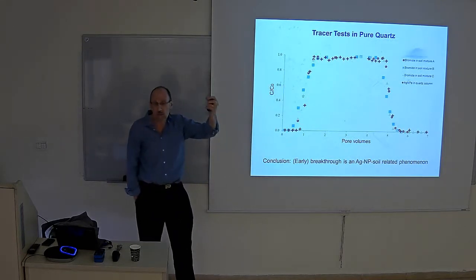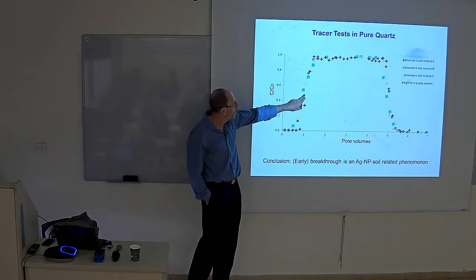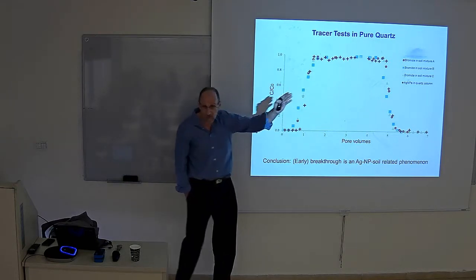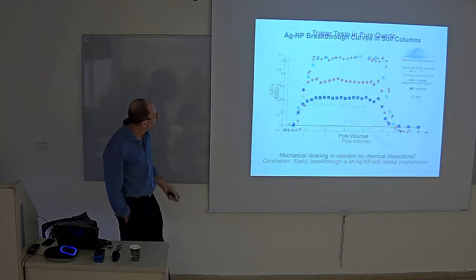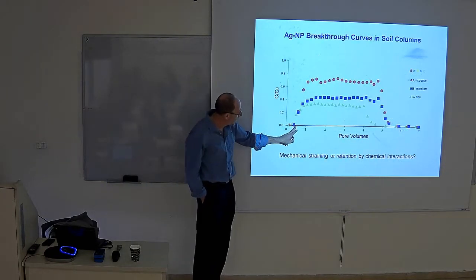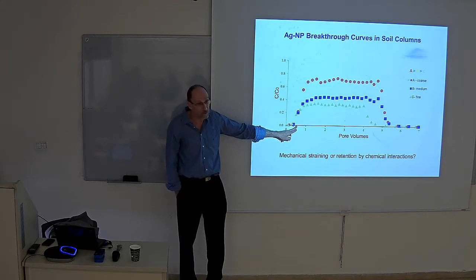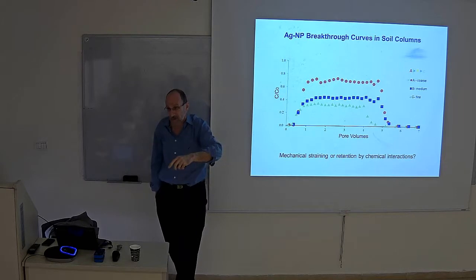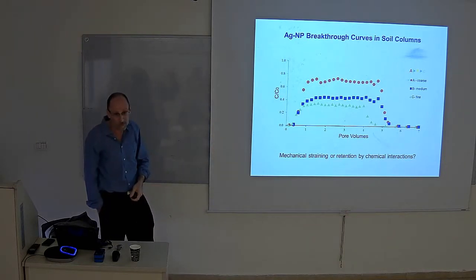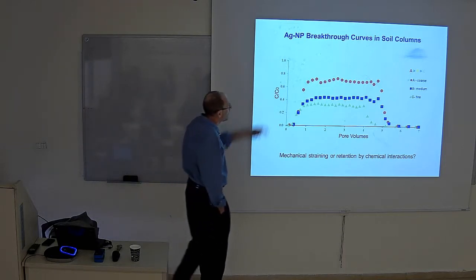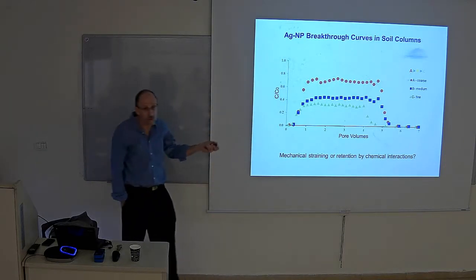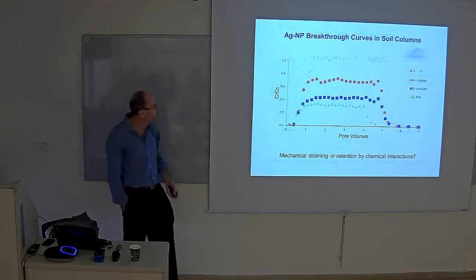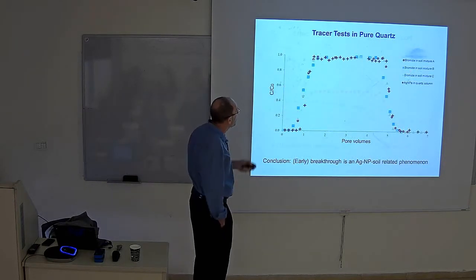You expect, with the conservative chemical, after one pore volume, the average concentration should be a half. Right? That's where the center of mass moves through. Then we look back at this one, and you find that you have first breakthrough much earlier than one pore volume. So a portion of the silver is actually moving much faster than a conservative chemical would behave. Why? If it's repulsive force is negative charge, well, silver is positive. I don't know. But you have now an early breakthrough and these physical chemical effects going on.